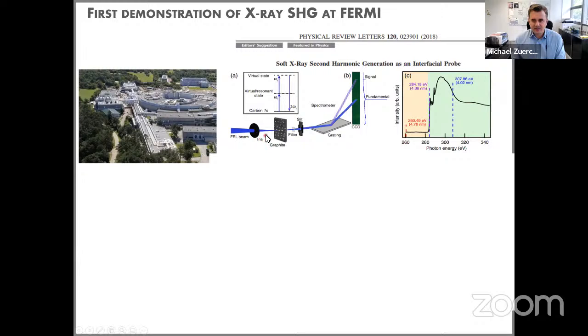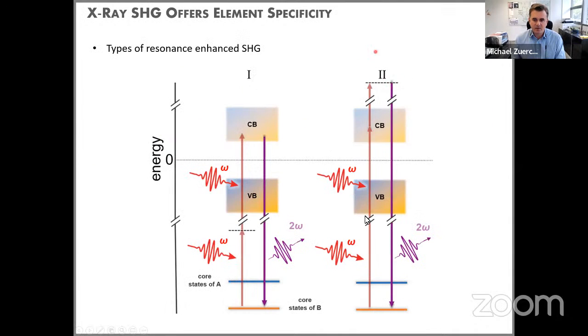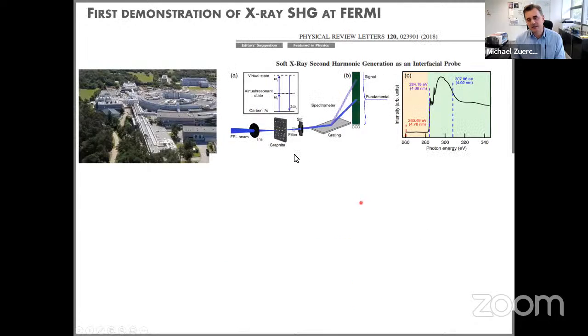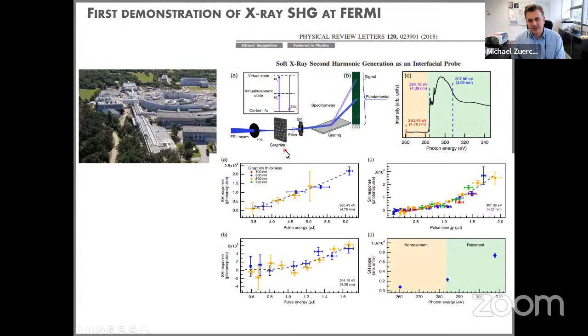And so in this very first experiment in the field, people focused on a graphite crystal. They went resonant with the 1s state of carbon to the conduction band and observed the second harmonic at twice the energy. So this would refer to this scheme 2 I showed here earlier. And then essentially the way these measurements work, and this was again the first work in this field, is you vary the pulse energy of your impinging free electron laser, and you measure with a spectrometer the signal at twice the frequency.